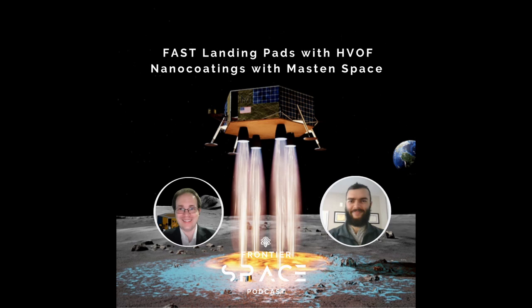That's just on the edge of where we would expect the regolith to start getting severely disrupted by the landing plume, and just high enough that we can still get the particles in the right thermal regime on impact. So it's all about thermodynamics in this one, thermodynamics and velocity. And then on impact, there's a series of splat equations from the HVOF coating textbooks that you can use, and also Hertz contact stresses for the solid particles that we use to build up the interface layer.